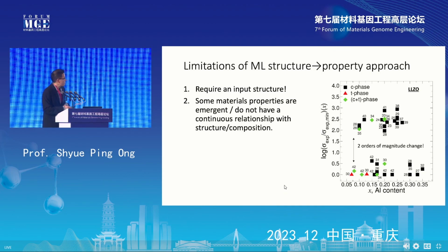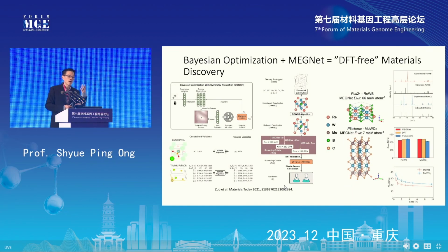So let me first show you how we can actually solve the first problem, right? If we want to get an input structure, can we do it without DFT calculation? And the answer is yes, right? We can actually combine Bayesian optimization with our MEGNet models to basically relax crystal structures without using DFT calculations, okay? So this was basically the approach that we developed in this work. There's a collaboration with Professor Jian Luo of UCSD, where we basically use MEGNet as an energy calculator, and we basically relax the crystal to the lowest energy form without using any DFT, okay?